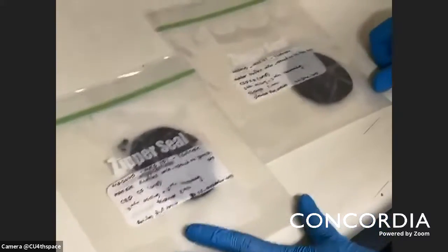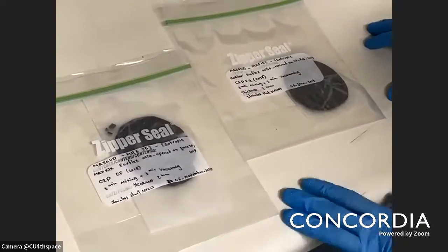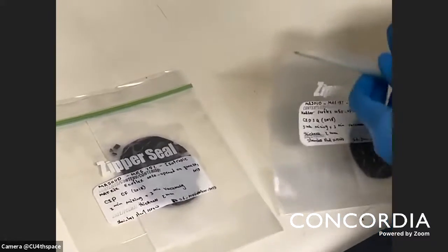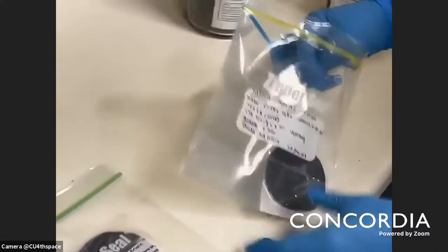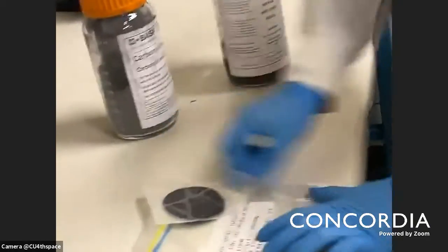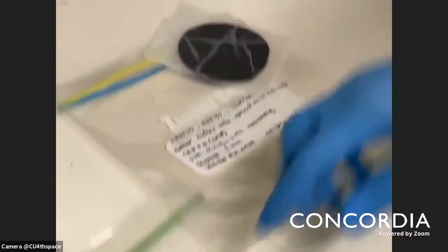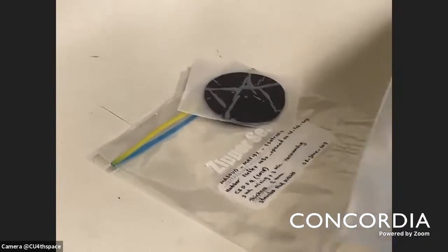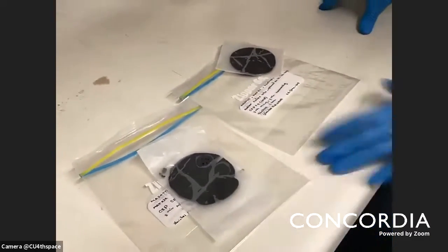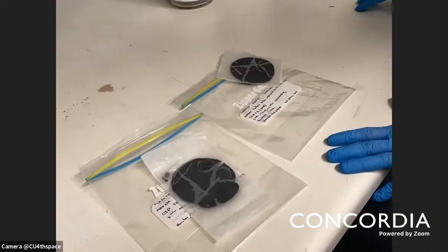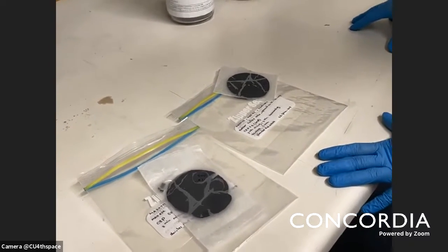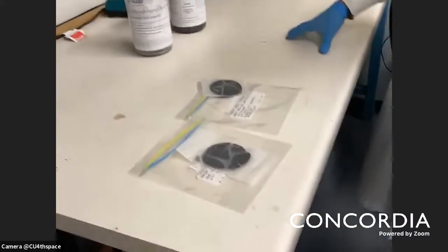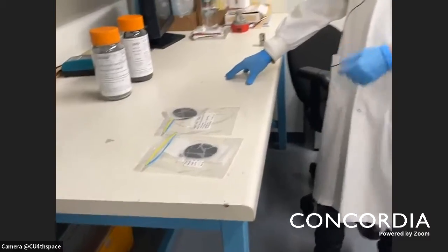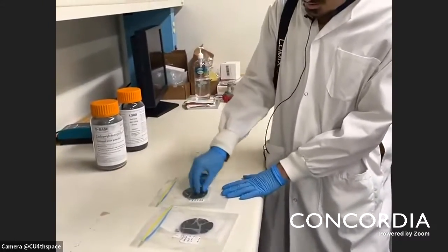As you see here, we have a silicone and the iron particles. In the fabrication process, we put the iron particles inside the silicone to make MRE here with different volume fractions. And here it is 25% volume fraction. The difference between this and this is that when you put more iron particles inside the silicone, you have a more MR effect. It means that you have more deformation or more response because of the iron particles.